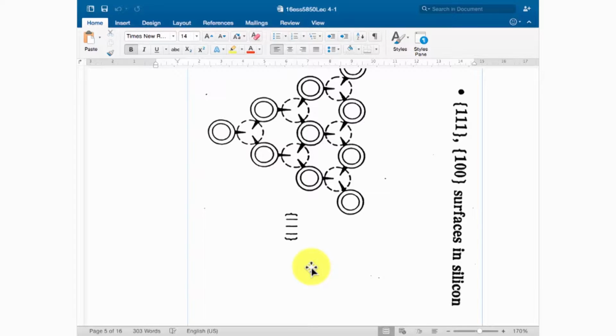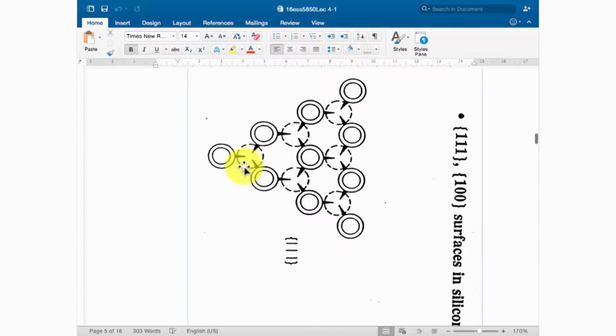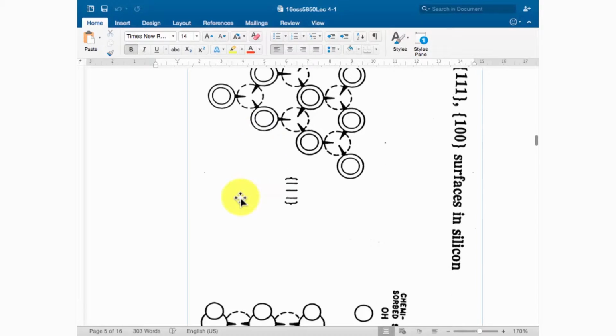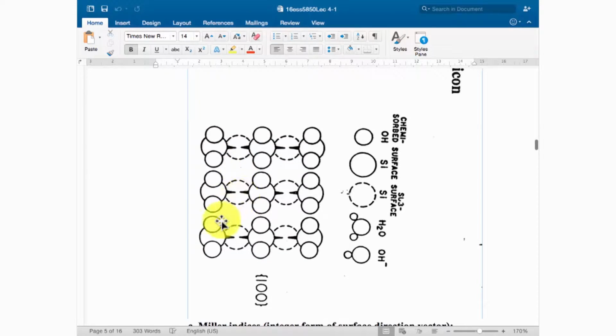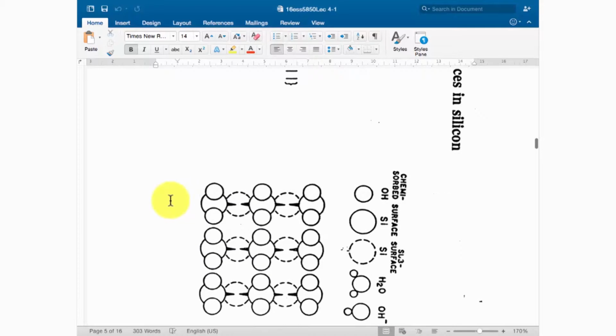So why do we concern ourselves with the orientation and also the density? Because afterward, we will discuss the etching rate on different phases. The 111 phase is the phase with the slowest etching rate. The etching almost stops here for some special chemicals. So this phase is an important phase. On the other hand, on the 100 or 110 surface, the etching rate is much faster than on the 111 surface. That's why at the current stage we need to understand the crystal orientation, in order to understand why the etching always stops at a certain kind of spatial structure and forms that structure. Okay, so now that gives you a rough idea.